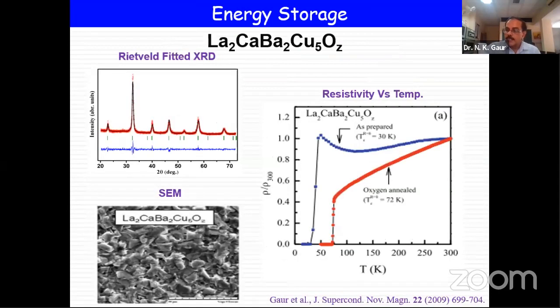This is again the second compound, La2CaBa2Cu5Oz, in which we have taken the RT measurement, Rietveld fitted X-ray diffraction pattern, and the scanning electron microscope picture. So by making these, superconductors can be used as superconducting coil.